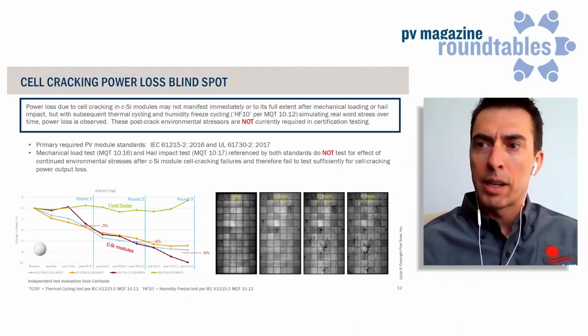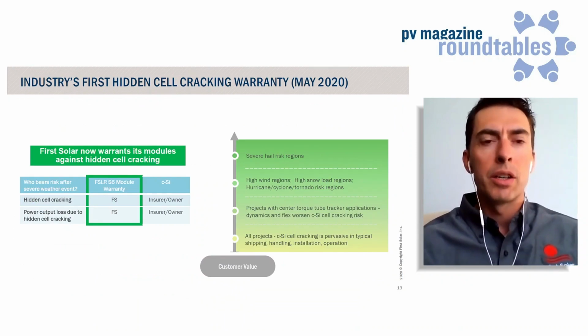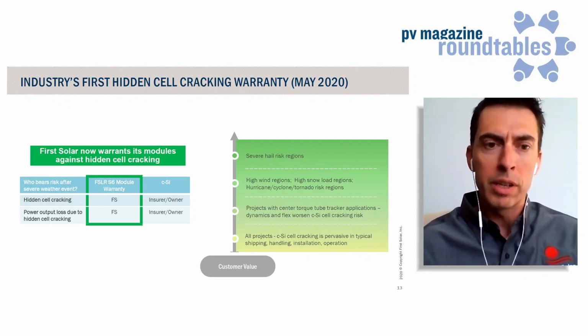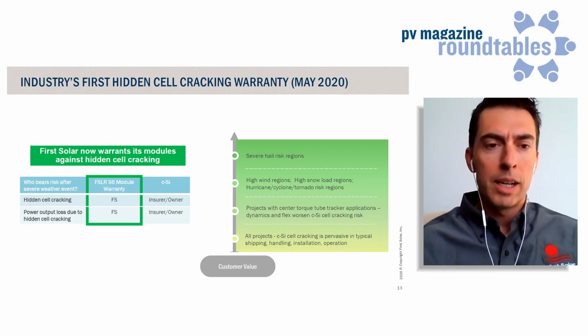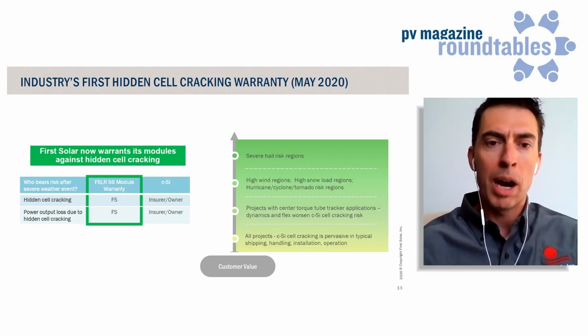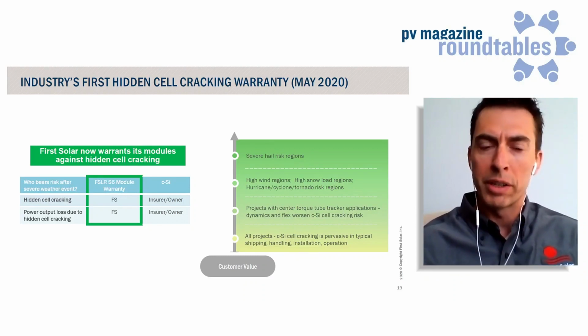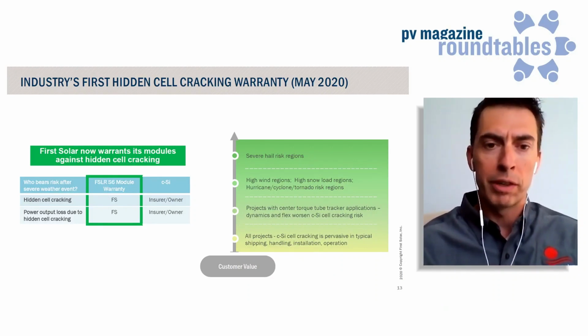So as we step to the next slide, what First Solar has been able to do with its uniquely differentiated technology and with its inherent immunity to hidden cell cracking is we've developed a warranty coverage that allows our customers to take advantage of that. We are warranting both the workmanship and power output impact that could be caused by hidden cell cracking, and do so for those scenarios while the glass remains fully intact in our module. We are guaranteeing that the cells in our module remain free of cracks and mechanically intact, and providing the output power that we have stood by for over a decade. So this coverage has a significant value in all projects across all regions, but most specifically and acutely in areas where you have exposure to severe weather or severe hail impacts.